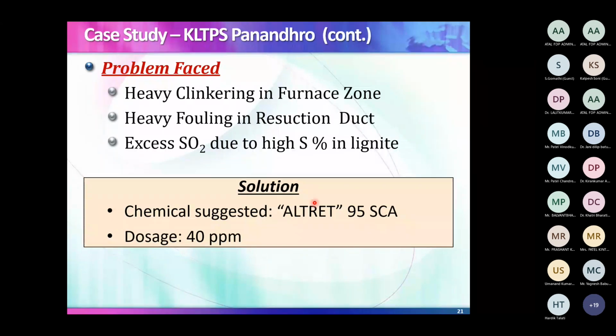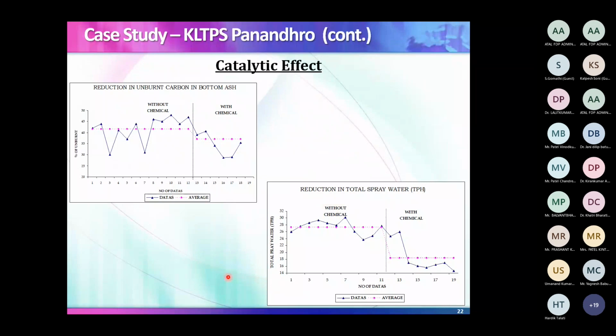What are the results? When you take out ash from the boiler, it has a large amount of unburned carbon. So without chemical, about 43% was unburned carbon, and with chemical, it has come down to about 33-34%. So there is a reduction of carbon content in bottom ash. Then there is a reduction in spray water. That means the heat transfer area of the tube has become much cleaner, and the steam generation is also improved. Spray water is normally used to control the temperature of the superheated steam, and the use of that reduced. That means some catalytic effect and anti-fouling effect is visualized. Without chemical, it was about 27 tons per hour, and with it, it reduced to 18 tons per hour. So this is also a sizable benefit.